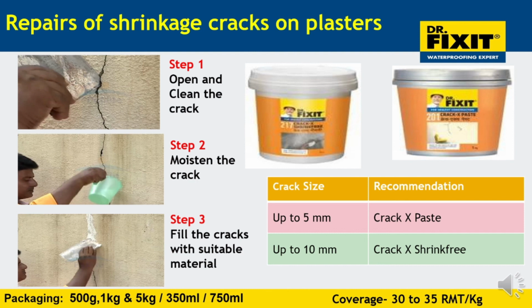Now let us see how to repair the shrinkage cracks on plaster. As I already informed you, but let us see with the help of these pictures. Step 1, open and clean the cracks as shown in this picture. Then moisten the crack and assess the condition. Then fill the cracks with suitable material. We have two products: Crack X paste and Crack X shrink free. Up to 5 mm use Crack X paste, up to 10 mm use shrink free.